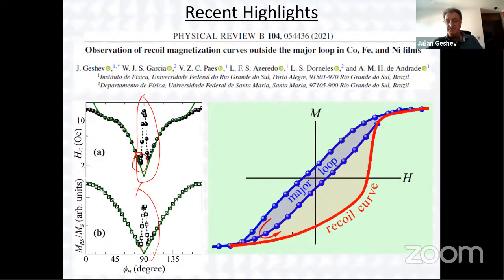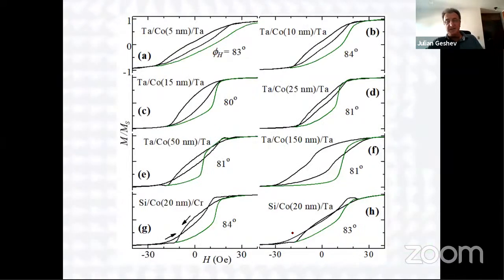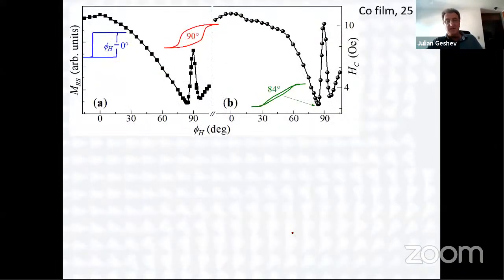What major loop means in this case, I'm not sure. It doesn't depend on the system, actually. We saw this in iron, nickel, and cobalt films with different thicknesses from 5 to 150 nanometers thick. The substrate doesn't influence so much. If the iron film is deposited on glass, you can do the same. And actually, we believe that this is quite a common phenomenon.